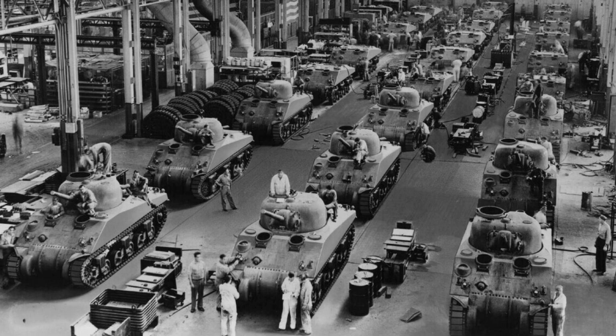The findings astonished even McNally. Of the 67 damaged tanks, exactly 0 showed catastrophic weld failure. Several had welds adjacent to penetration points, where the armor plate itself had been punched through. The welds remained intact even when the surrounding metal had failed.